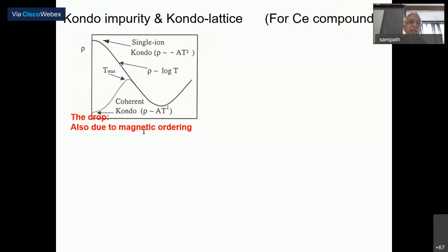In any case, if you look at the electrical resistivity as a function of temperature, over and above the minimum, in some Kondo lattices you will have a drop because of coherent scattering, which I will not go into detail now. But this drop is also the signature of a magnetic ordering at that temperature. If we take a magnetically ordering Kondo lattice, where RKKY dominates over the Kondo effect, this is a typical feature which you expect here. Therefore, I request students to remember that this is the typical feature for a Kondo lattice where you have a magnetic ground state, where magnetic ordering is the dominant one.